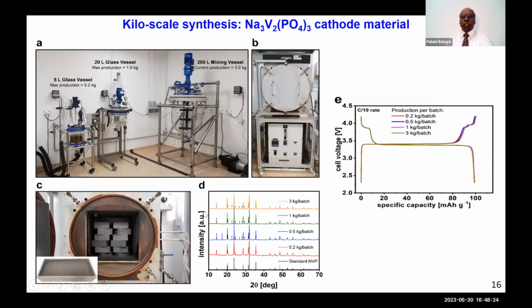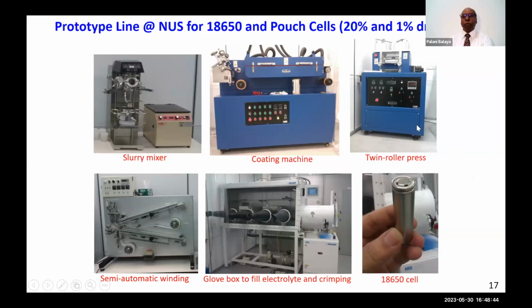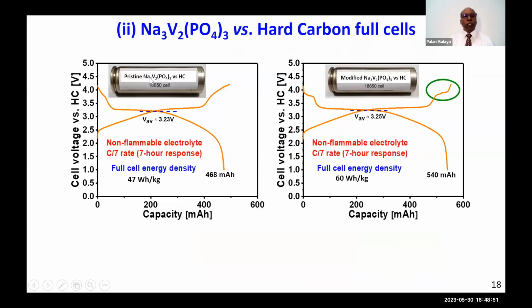And we have a so-called kilo scale lab. We normally scale up the production from 200 gram to about 3 or 4 kilogram per batch. And you can see the performance is pretty good. For every batch, we test the performance, and the impurity levels are within the acceptable level that doesn't affect the storage performance, as you can see here. And we do have a prototype line, 1% and 20% dry room, where we can produce some of these commercial type cells. So I'm showing you here sodium vanadium phosphate pristine versus hard carbon as the negative electrode.